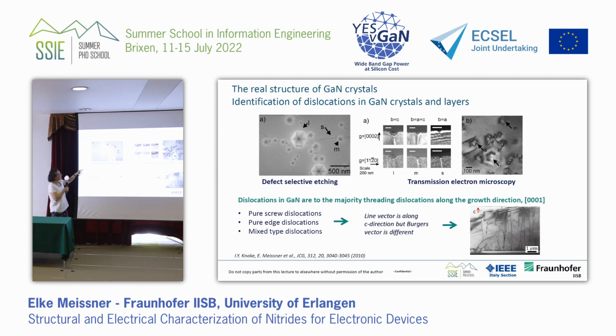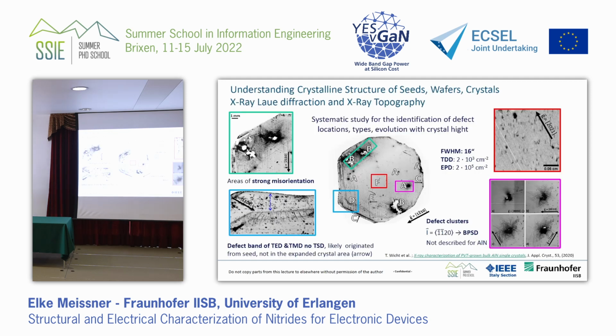And then you see really what type of dislocation is where, and you can make statistics over your crystal. You say, okay, the whole area of the crystal that I investigate now, if you would go back and imagine the picture from before, then you see, okay, now if we etch such a slice, we see that there will be many etch pits, and we see, okay, this is a different type of dislocation than that, and this and that. We can investigate such types of dislocation, and we know, okay, they are basal plane dislocations, so they may not appear at the surface, so may not play a role in epitaxy. But such ones that emerge to the surface, they play a role in epitaxy.